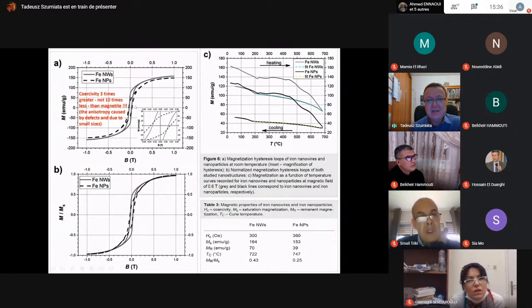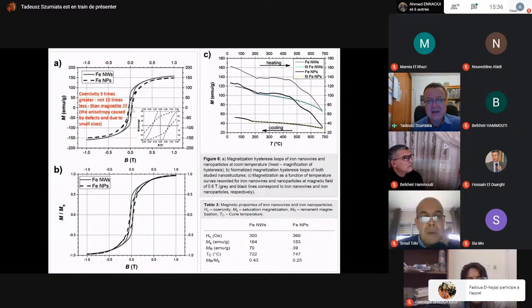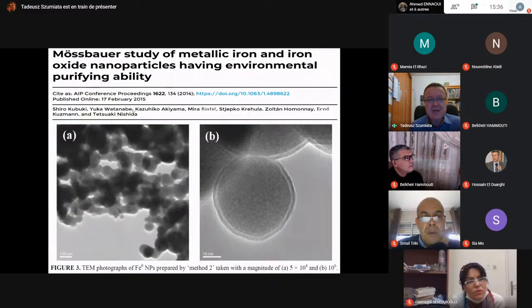And when we look at the hysteresis loops, you can see something strange. Okay, no wasted feature because it is not a mixture. But if you look at the coercivity, this coercivity is not 10 times smaller than magnetite. It's 3 times higher. It means that so defected and so small particles of metallic iron have so hard magnetic properties, and very similar to the magnetite.